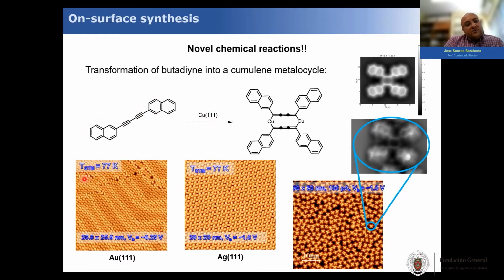When we deposit them on top of gold and silver surfaces, nothing occurs. You just can see how the molecule, the precursor, tessellates, completely covering the surface. It's a really nice pattern, but nothing occurs. But when we move to the more reactive copper surface, what we can see here is quite a transformation. You can see these small crosses that, in my opinion, look like chromosomes.